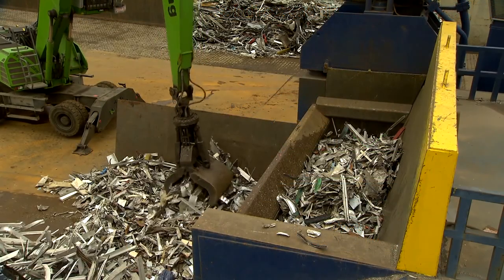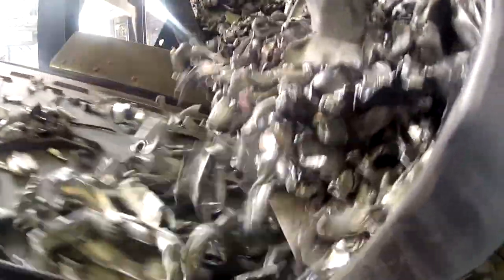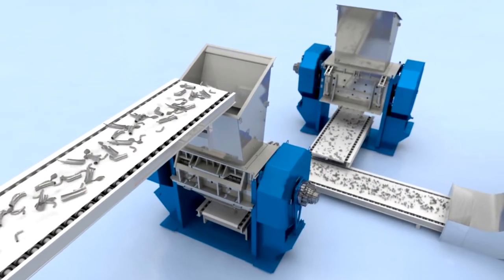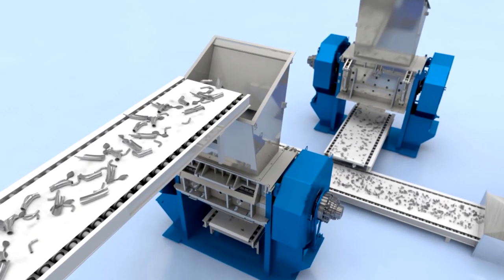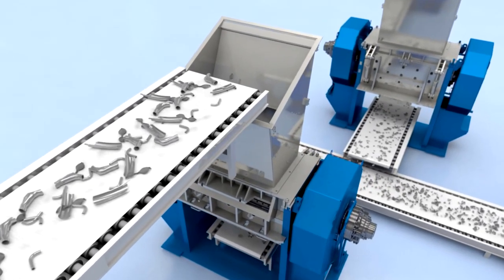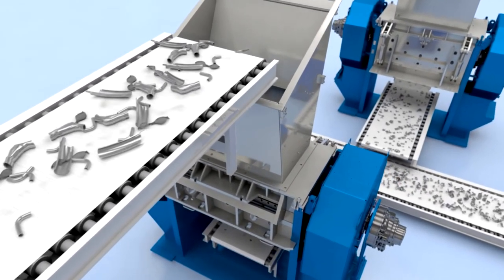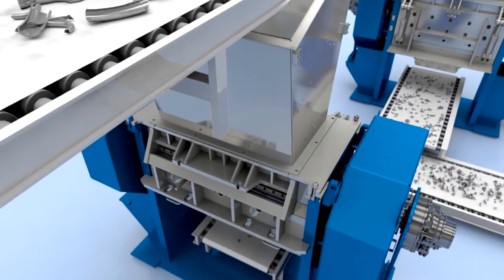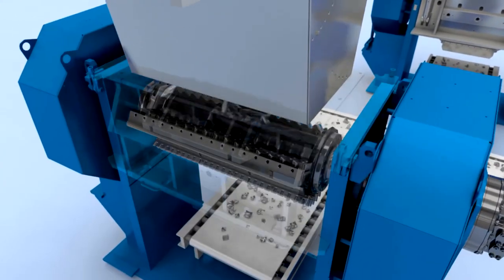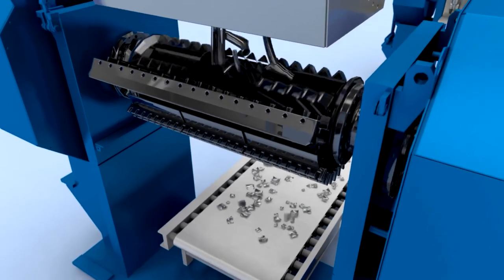Let us look closer at the recycling of aluminium alloys. These materials can usually not be mixed among the different grades, but must be carefully sorted prior to remelting. This is due to the fact that current aluminium alloys are highly optimized for strength, ductility, surface appearance, corrosion, toughness and formability, to name but a few key features.